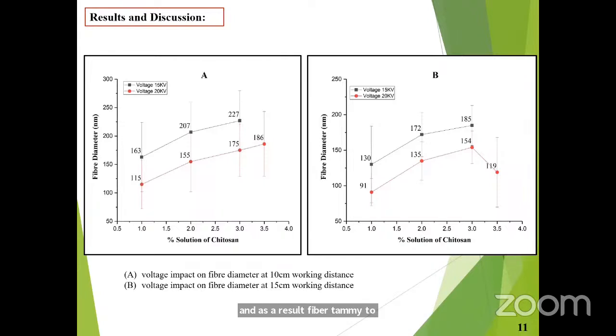Apart from the working distance, applied voltage, which I already explained, is also really important to study regarding nanofiber morphology. Results show that the average fiber diameter of chitosan nanofibers was also reduced with the increase of applied voltage from 15 kV to 20 kV while keeping the other process parameters and working distance constant.